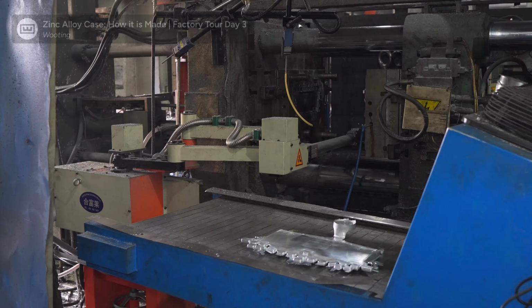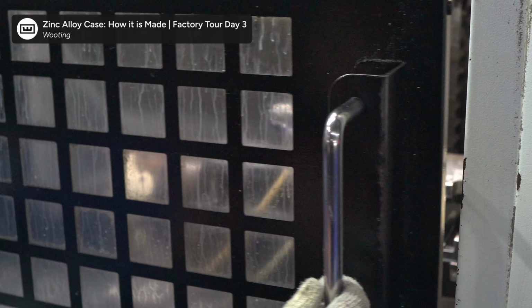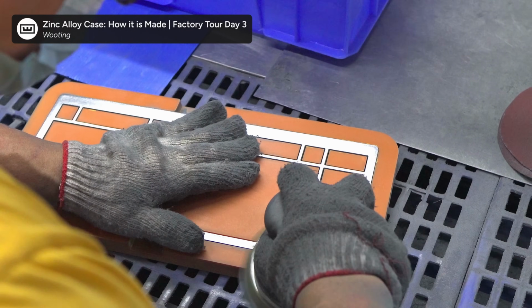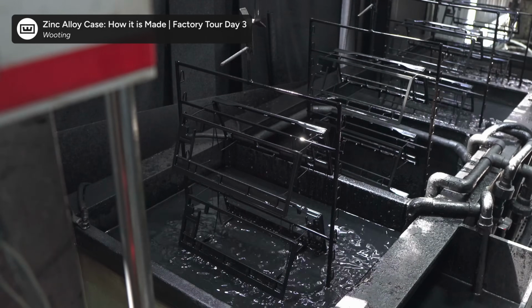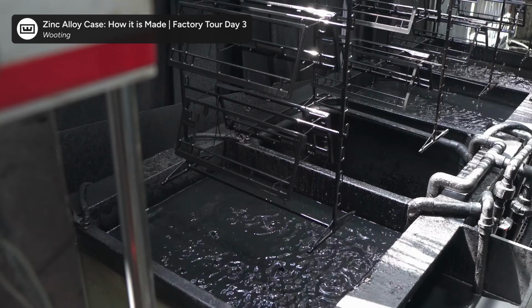So the first response to this coming up from a single customer, to be very clear, of thousands of these cases already being sent out, is that probably it's related to a quality control issue. And the quality control meaning that every time we make one of these products, it goes through the whole process. In this specific case, with the Black Zinc case, you have the whole die casting of the zinc case. Then it gets CNC'd, it gets polished, it goes to e-coating, a specific nano black e-coating, and then it goes through an oven hardening the coating, and then we have our Black Zinc case.